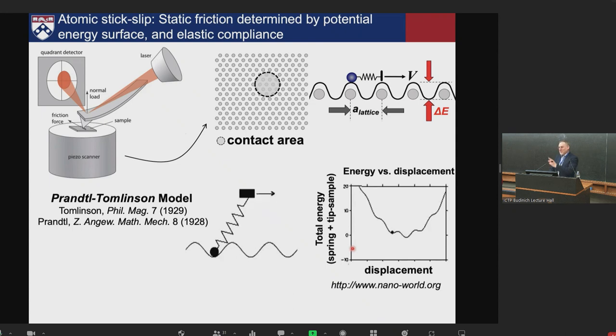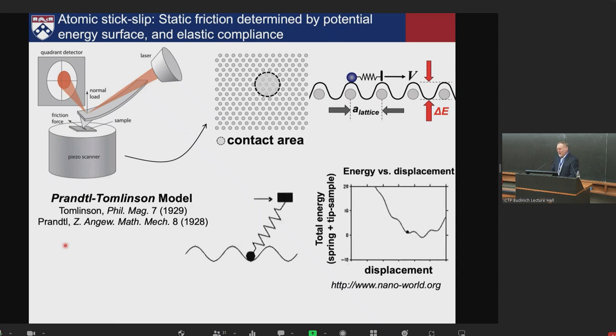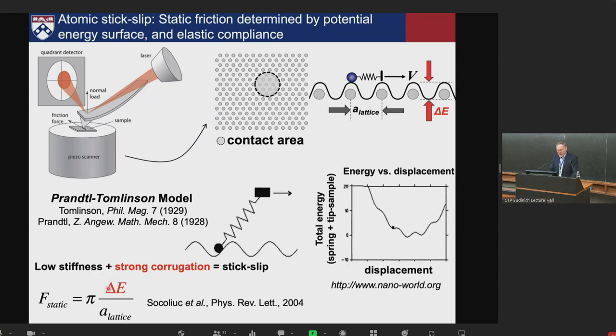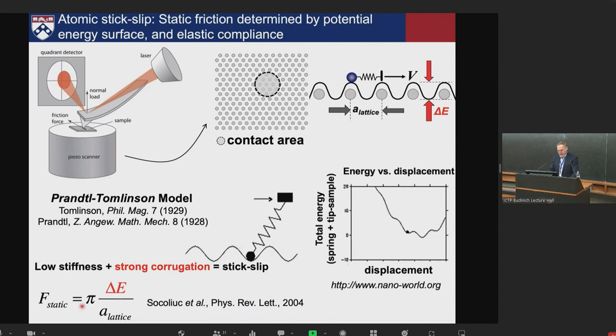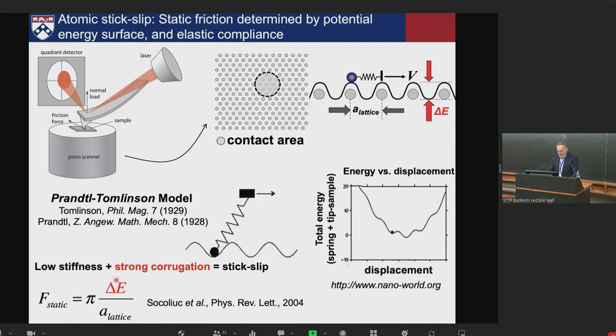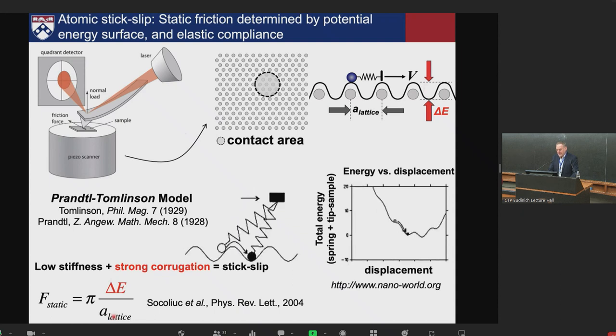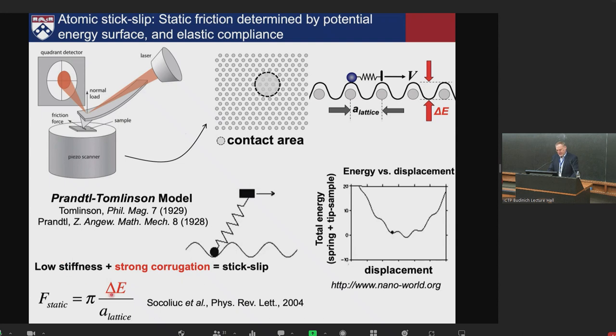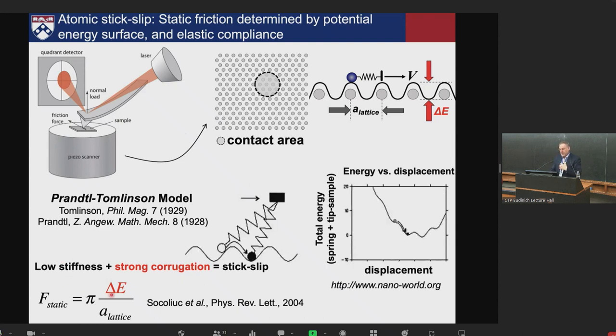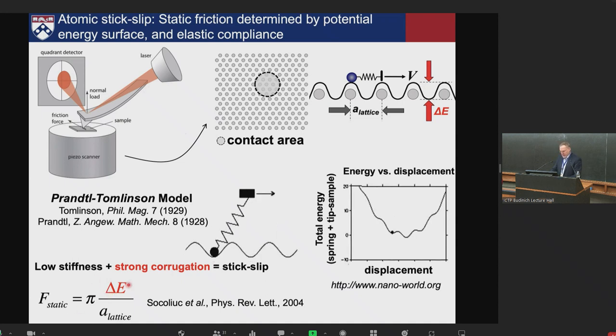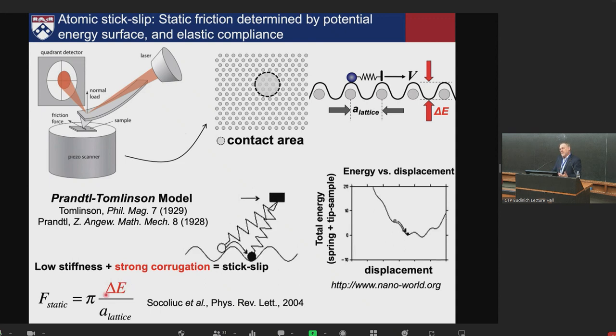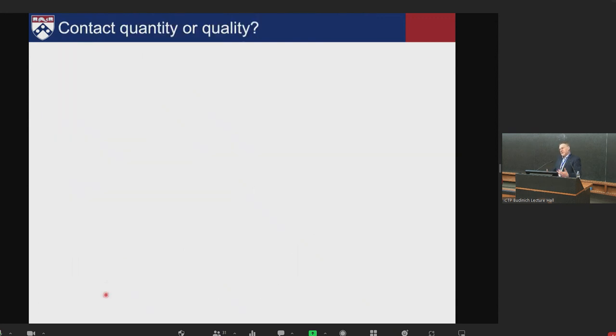And Enrico Gnecco and Roland Bennewitz in the audience are people that helped figure out the right way to describe that early on. So the key parameters in getting the static friction force out of this model are the corrugation of the potential energy surface, this delta E, and the lattice spacing actually comes in here as well. So this is a very simple relation. This is, again, zero temperature. There are speed effects, temperature effects, but a very simple relation. And this is what I want to focus on: what is it that determines this energy barrier? And what happens as you change the conditions?